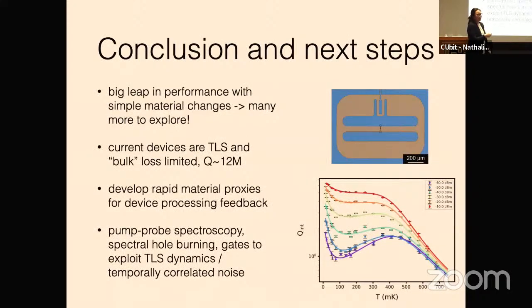But maybe the takeaway message here is that we had an enormous leap in performance from just trying a new superconductor, right? And sort of charitably, the superconducting qubit community had tried like 4 or 5 different metals for their superconducting qubits, and we added 1 and managed to move the state of the art by about a factor of 3. So I can list another 20 superconductors that you can kind of easily deposit in thin film and fabricate. So I think it is now time to start doing the more systematic search through material parameter space.